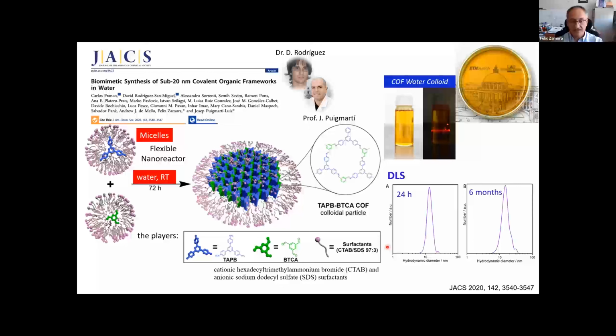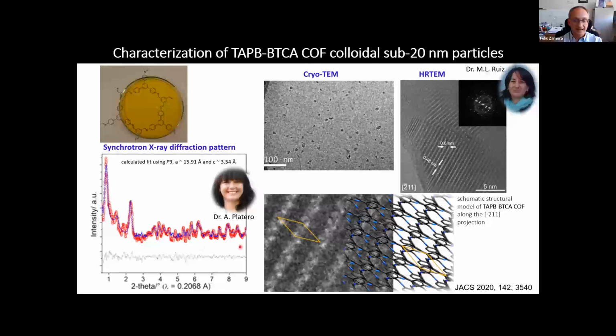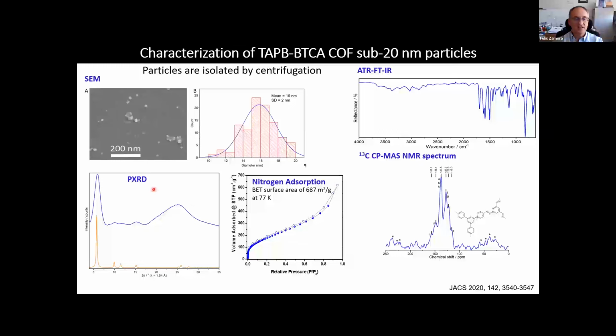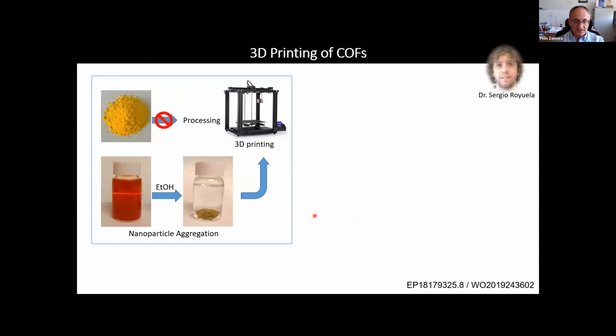This is just to show you very briefly, because we are short on time, the characterization of the nanoparticles. You have crystallinity coming from this colloid, you have ordered structures, you have porosity, you have everything. And I'm telling you this because we observed that when you add ethanol to this water colloid, you can control nanoparticle aggregation of this material. And then we thought, why don't we try to use this to 3D print our material?